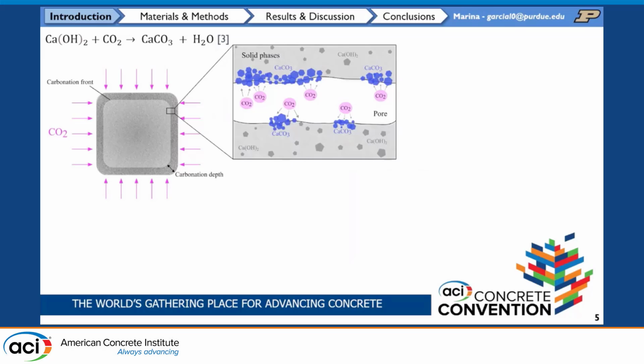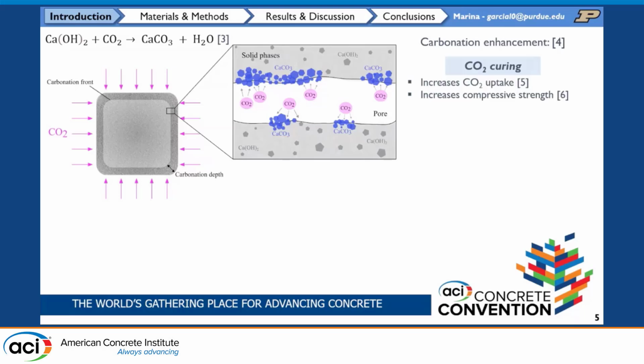What happens with this reaction is that CO2 will penetrate through the pore structure, and it will react with the cement hydration products that are in the solid phase of our matrix. Mainly, it's calcium hydroxide reacting and forming calcium carbonate and water. So if we can enhance this reaction, whether that's accelerating the reaction or enhancing the amount of CO2 that it's uptaking, we can lower our environmental impact when we have this material. One of the approaches that is usually taken is CO2 curing, which has been found to increase CO2 uptake, and it also provides better mechanical properties in some cases.